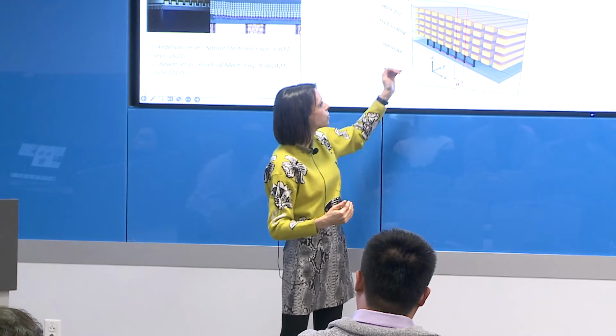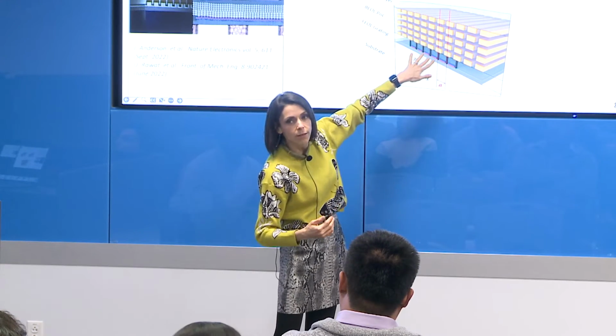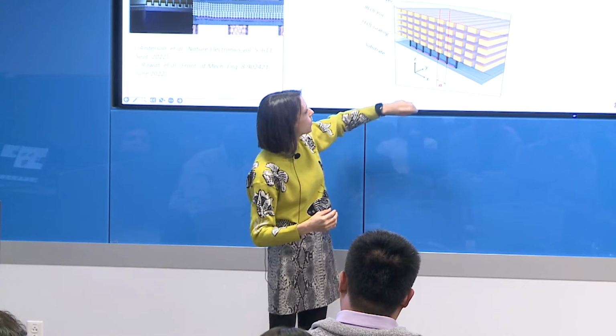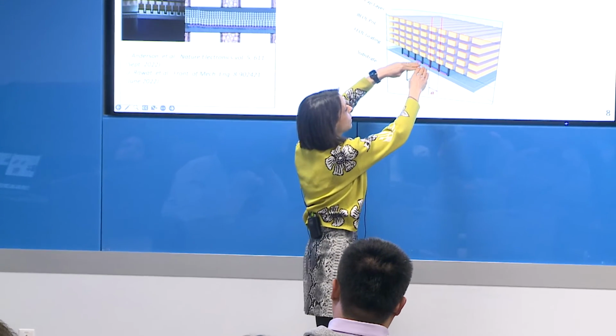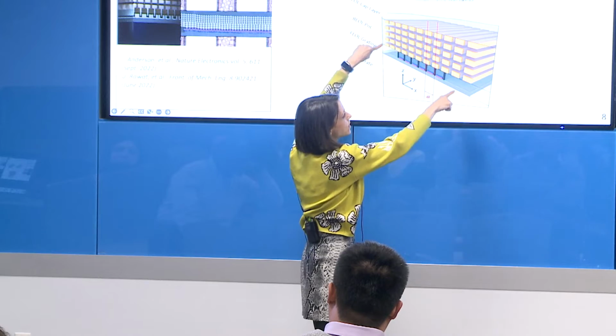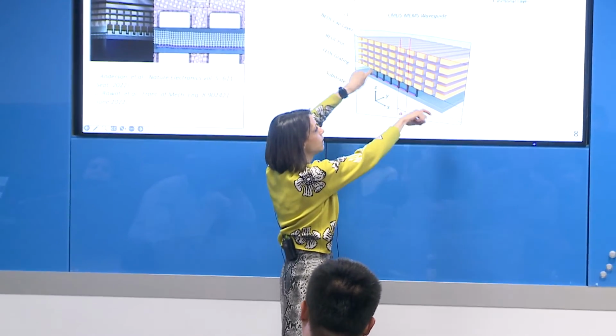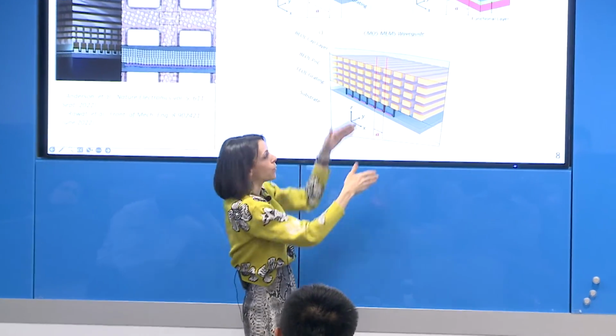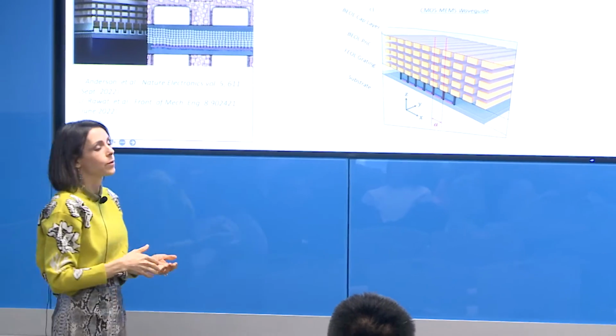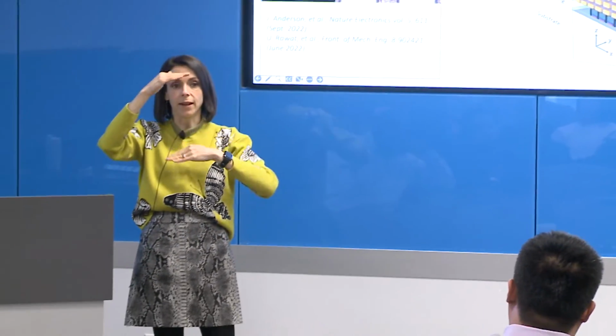So what we'd like to do is launch acoustic waves in this front end where all the transistors are, and then ensure that the vibrations stay in plane and that they terminate at some point, okay? So first part was getting the in-plane vibrations, making sure we don't lose acoustic waves above to the metal layers or down below to the substrate, right? And so this involved basically engineering that entire stack.